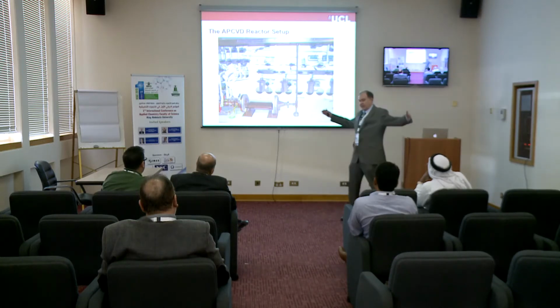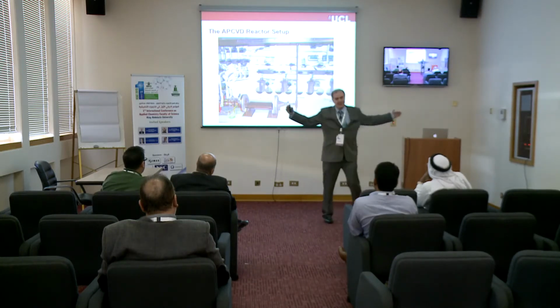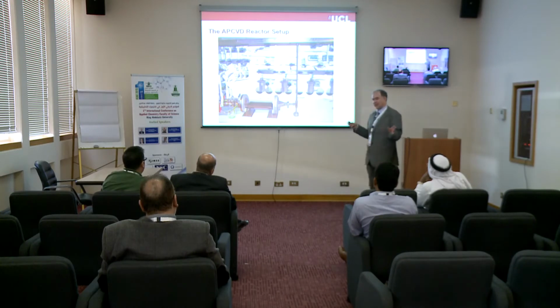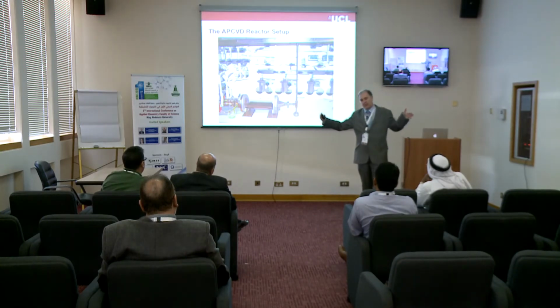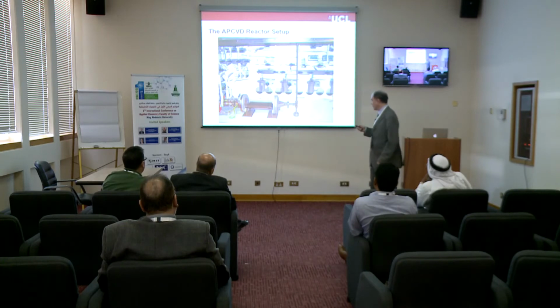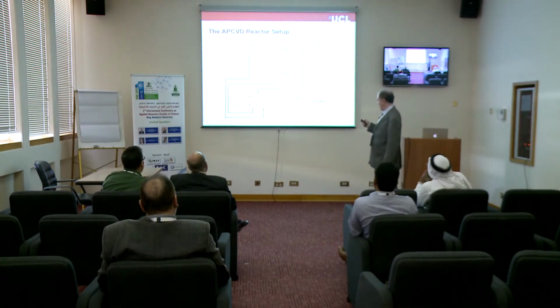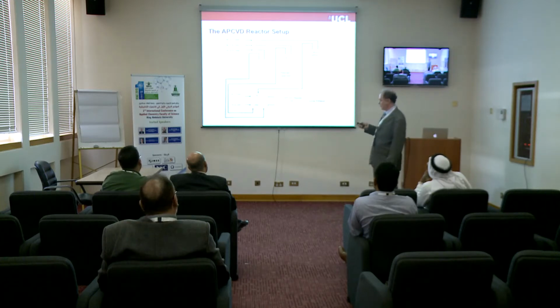We sometimes scale things up to about 1 metre to make coatings, and when we do it industrially, we do it on a metre wide ribbon, about half a mile long, on a rolled glass line. For making titanium dioxide, we use titanium tetrachloride, ethyl acetate, and sometimes we put some nitrogen dopant into the system. And essentially, as the gas comes in, we get deposition on our glass substrate.